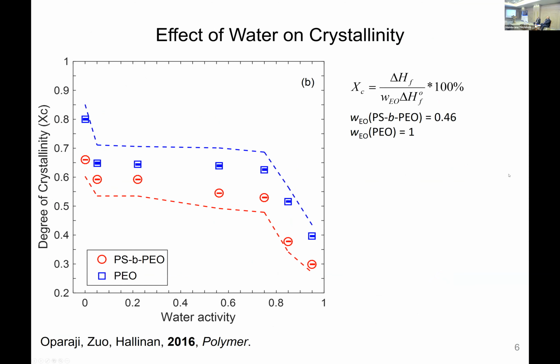So we took this polymer and did some studies on it. The first thing we did was equilibrium measurements. We equilibrated it in different relative humidities, and then measured the degree of crystallinity. Polyethylene oxide is a semi-crystalline polymer, and we have a control here.